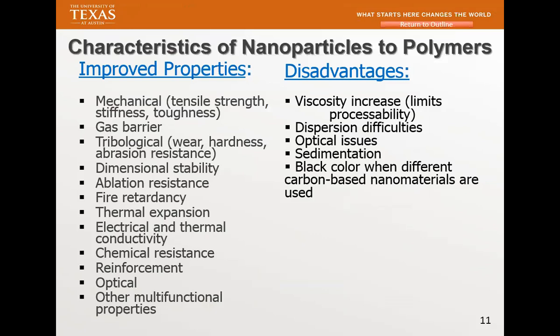You put the clay in your polymer, can be thermoplastic, can be thermoset, or thermoplastic elastomer. Roughly 5%. You look at the literature, you'll find that. You put more than that, it's going to hurt your mechanical property, and that's what you want to watch out for.